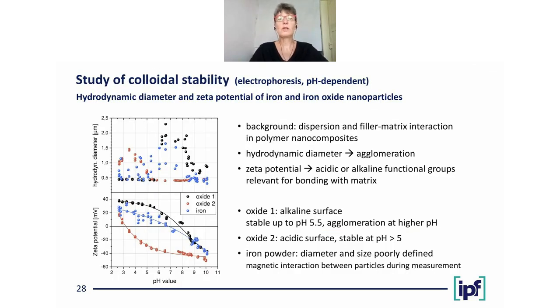Of course, we also deal with colloidal stability. Here you can see at the bottom the zeta potential, at the top the hydrodynamic diameter of different iron oxide nanoparticles, and for comparison of iron powder, these are the blue dots. The background of this research is the dispersion of these particles for use as fillers in polymer nanocomposites. For this, both the dispersion, the dispersibility, and the filler matrix interaction are of big importance.